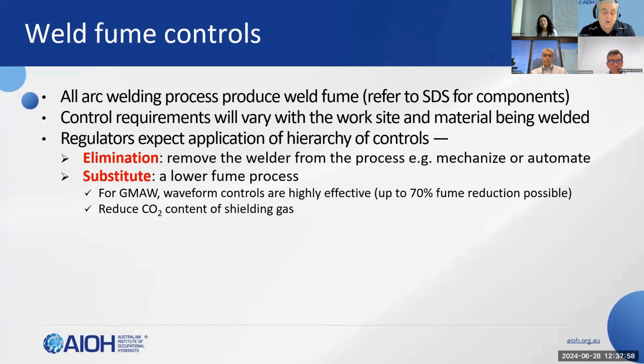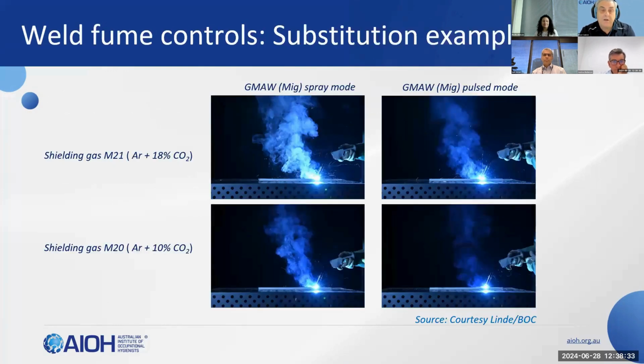Another alternative is that you can use processes that produce reduced rates of fume, and this may be a viable option. This is particularly potentially viable if you're using the gas metal arc or MIG process, where waveform controls, for example, can reduce the fume generated by up to 70%. I should add that lower emission welding consumables are also now being developed by consumable manufacturers. Now, in the next slide, this slide now shows clearly some benefits from applying waveform controls if the power source is fitted with such an option.